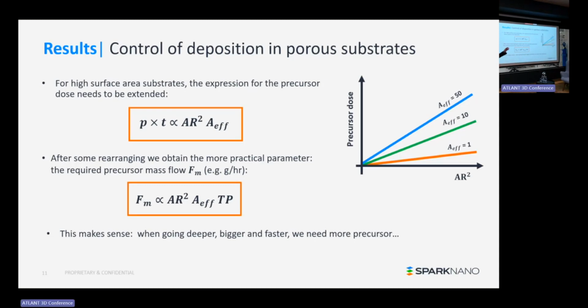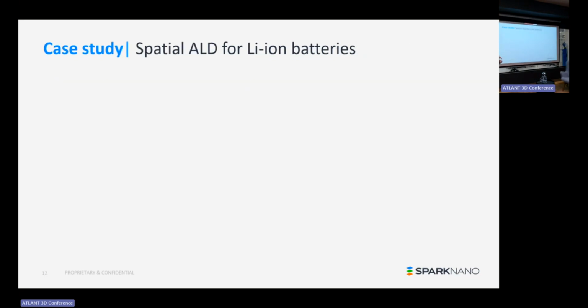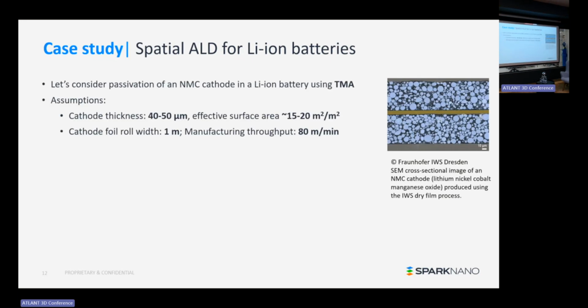This is all still very qualitative. Using this mathematics, we can actually calculate how much precursor we need to supply, taking into account transport and diffusion and waste and all these kinds of things. So as an example, I did some calculations for a lithium-ion battery case. Suppose we have an NMC, nickel, manganese, cobalt oxide electrode for a lithium-ion battery. We want to passivate every individual particle with aluminum oxide using TMA as a precursor, so nothing fancy.